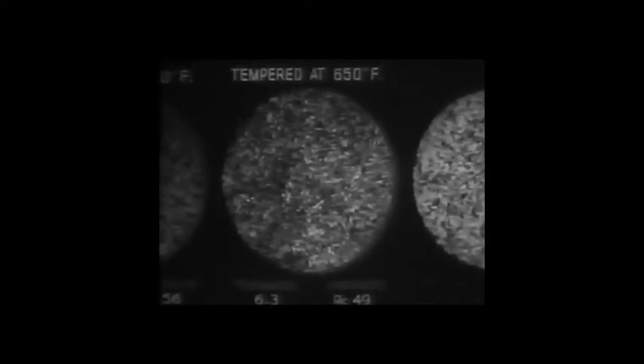After tempering at 400 degrees Fahrenheit, only a very slight change in structure has taken place. It is still essentially martensitic. Point 2, and by its Rockwell C reading, which is down 4 points to 56. When the steel has been tempered at a higher temperature, 650 degrees, a recognizable change can be seen in the structure. The carbide has started to precipitate from the martensite. The carbide appears black in the micrograph. The toughness, however, has barely changed. It is now at 6.3, even though the hardness has decreased to 49.